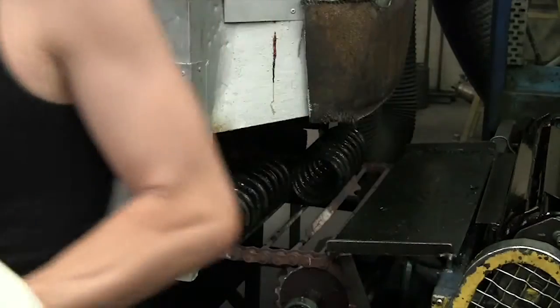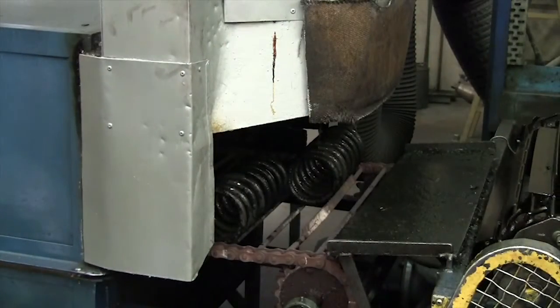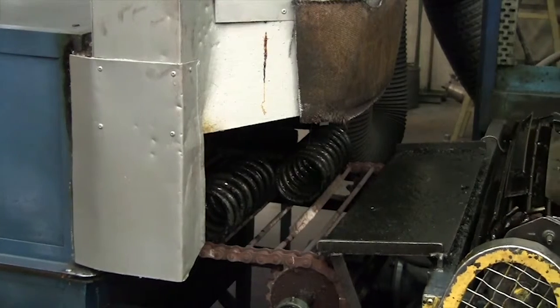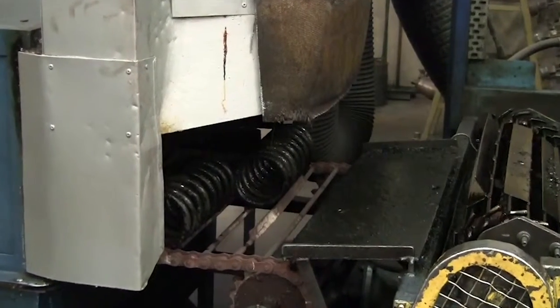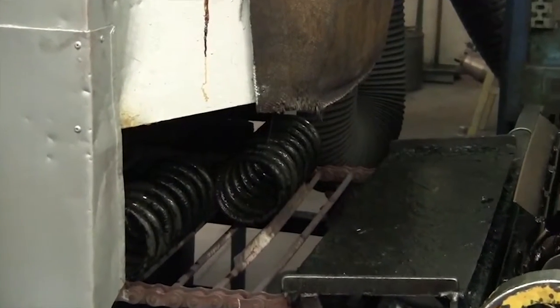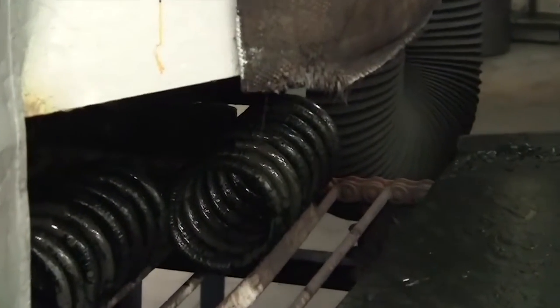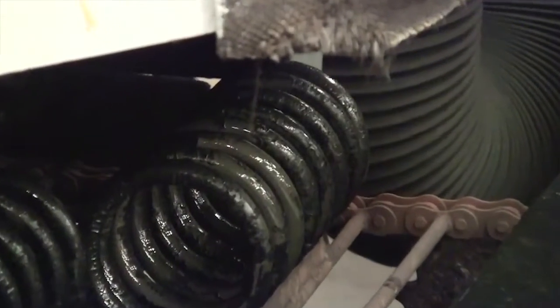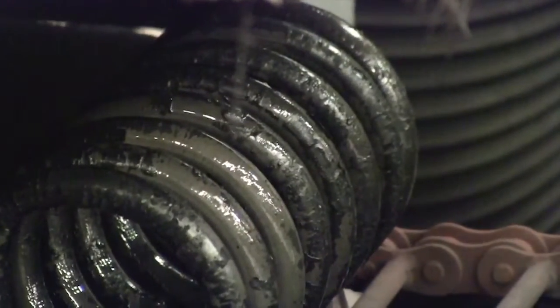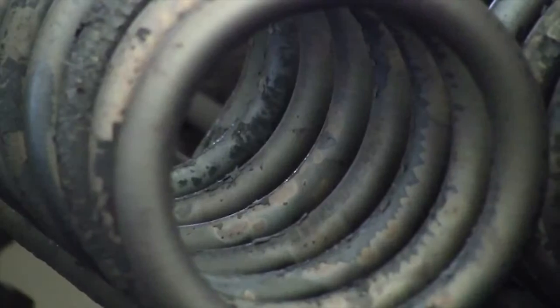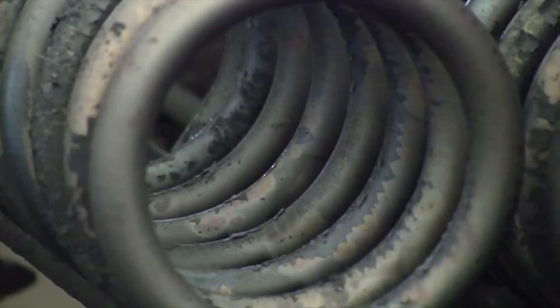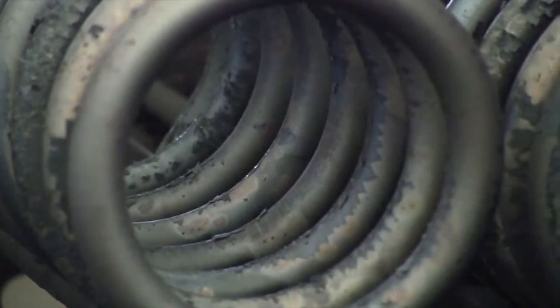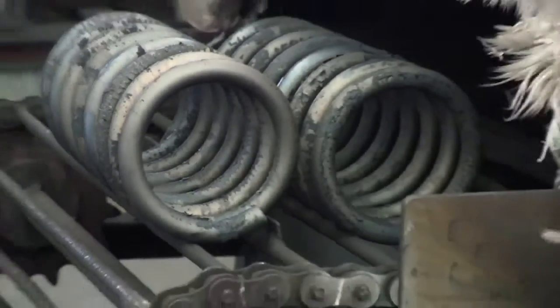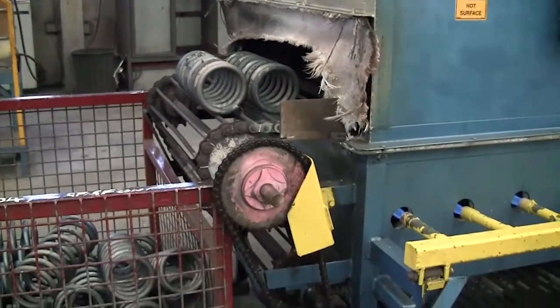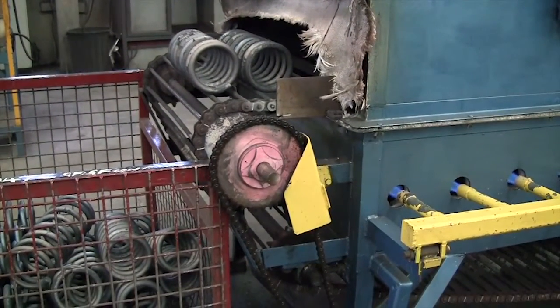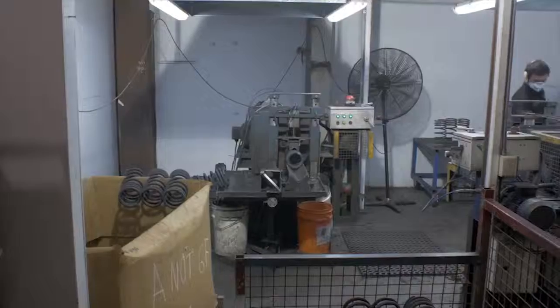From here, they pass through the gas-fired tempering furnace with an even temperature distribution that varies according to the spring wire diameter. This process ensures that the material maintains its elasticity. This segment of the procedure is very slow, as there's a need to heat the material uniformly from the exterior to the core, thus not creating any weak segments in the material. A good coil spring must return to its designed shape after a deflection. If a coil is not tempered correctly, there's a good chance that it will collapse.